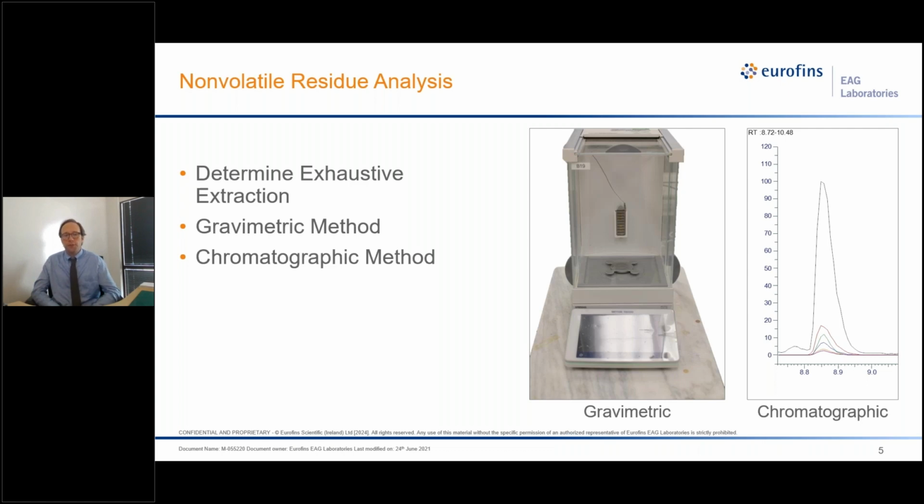The previous thing I alluded to is really the gravimetric method, right? So we take the sample, we dry it completely in a tared container, and then we simply measure the mass. What's nice about doing a gravimetric measurement is that, a balance in a sense is a universal detector, right? If you have matter and it's enough that it's a mass that can be observed by the balance, it will be observed, right? And so this is kind of an orthogonal approach to the instrumental techniques.